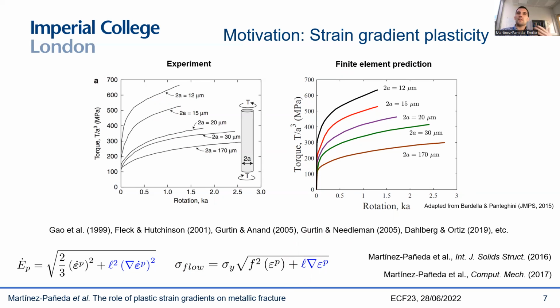So when you fit that length scale, that typically gives you a value between 1 and 10 microns, you see that you're able to get a very good agreement with experiments. And these are finite element predictions of those experiments on thin copper wires, and these are from Lorenzo Bardella and Andrea Panteghini, and you can see that they get a very good agreement. So we are able to use these strain gradient plasticity models to predict what is the role of GNDs and plastic strain gradients. So this is what we want to do in fracture.